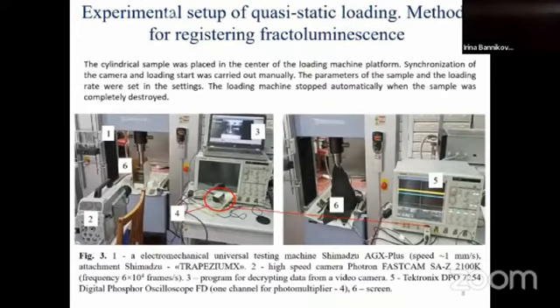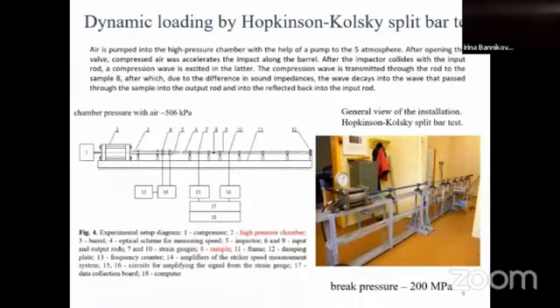Quasi-static compression was realized on an electromechanical universal testing machine performing axial loading. Fractoluminescence was registered by two methods. In the first, the joint operation of a photomultiplier and oscilloscope was used. In the second, a high-speed video camera was used, which recorded the destruction of the sample and fractoluminescence. Dynamic loading of cylindrical samples was done by a Kolsky bar setup. Fractoluminescence was registered by photomultipliers and oscilloscope.